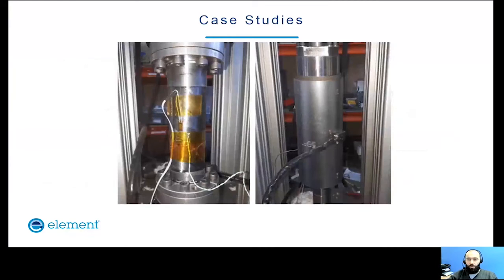We also would like to talk about the importance of temperature control in fatigue testing. The frequency of the loading experienced by the pipeline in service is normally much lower than what we apply in the qualification programs. The reason being, the tests are run at higher frequency in the qualification to get the total number of cycles required for qualifying the pipe in a reasonable time. Due to internal friction between the composite layers, the higher frequency might result in an increase in the test temperature, which can result in accelerated failure of the parts. Hence, it is vital to run an adaptive test which monitors the surface temperature of the coupon and pauses the test when the increase is beyond a set limit. This set limit is normally about 5 degrees C, and then resume the test after the temperature drops back to its original value.